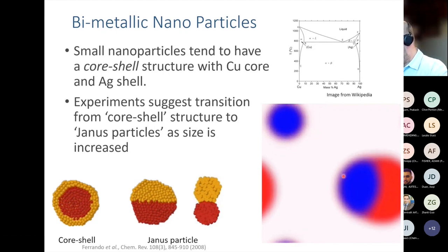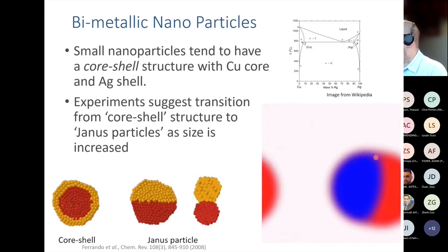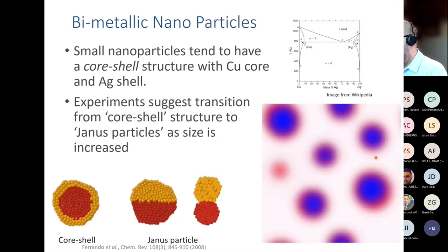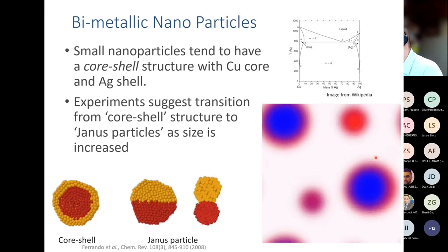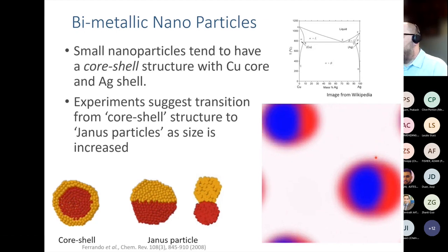They have a dumbbell shape with a groove in between the two, which is as expected because, of course, that forms a triple point, and then all the dihedral angles have to be fulfilled, and we have the competition between the different interfacial energies there.